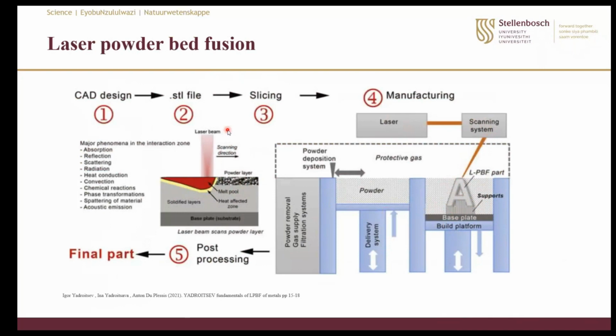That is what we called a keyhole porosity. And the worst of them can either be a gas trapped in the melted pool or some powder being trapped in the cavities, and we call that one the spherical porosity. But then it is not so ideal to physically cut through your object after you've printed it.